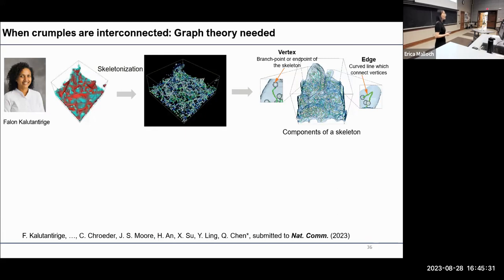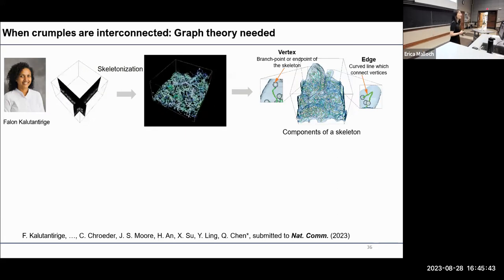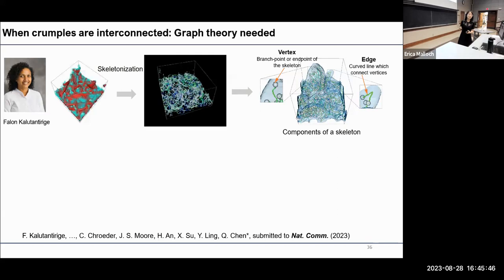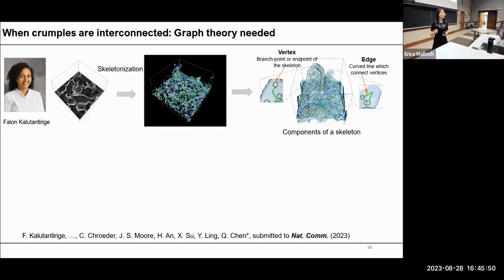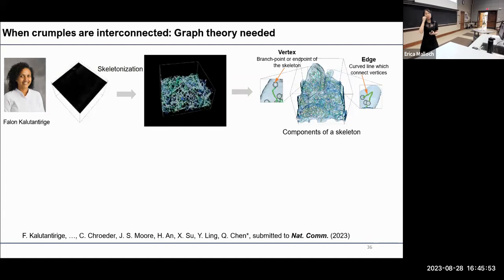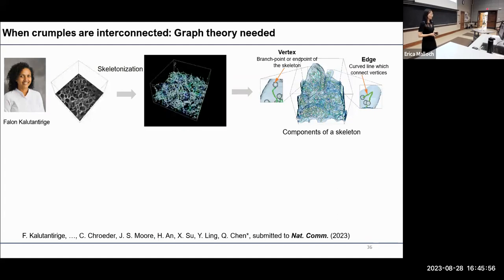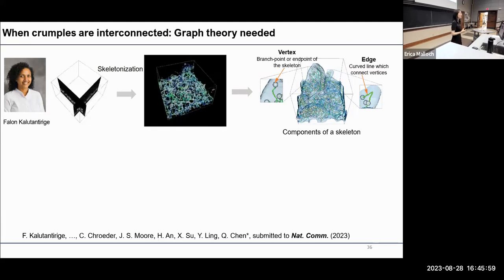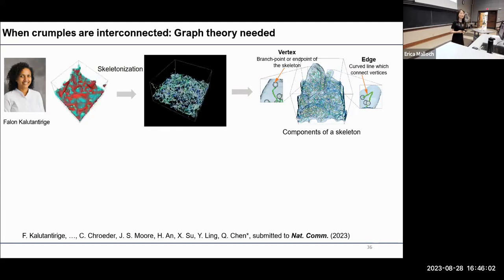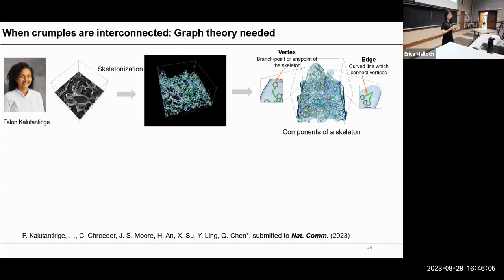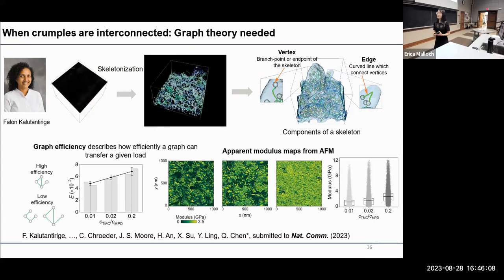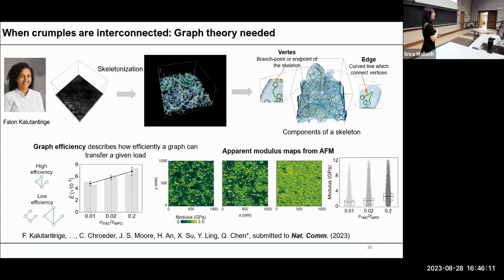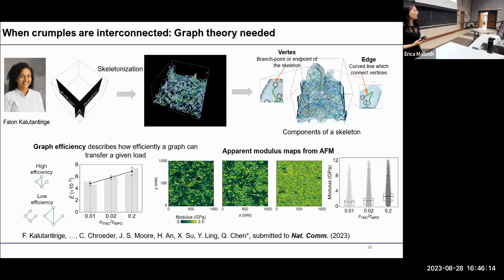So this is when my student Fallon came up with this very smart idea of using graph theory. In particular, she was able to apply skeletonization onto this electron tomograph to simplify it into a network as shown here. This is a network composed of vertices and edges. And this is a network that is essentially the structural graph of our complex morphology. This is a really important conceptual leap because then we can connect with a huge mathematical toolbox in graph theory to quantify this network. For example, we can use a so-called graph efficiency, which describes how efficiently a graph can